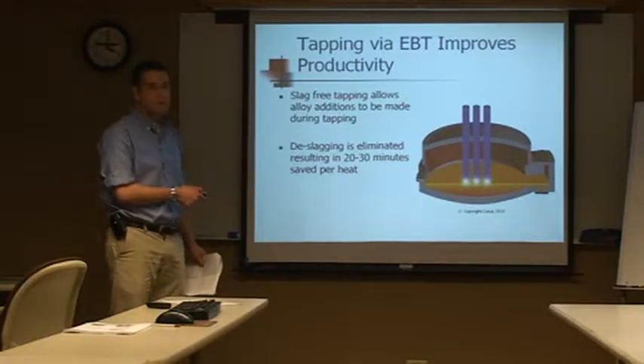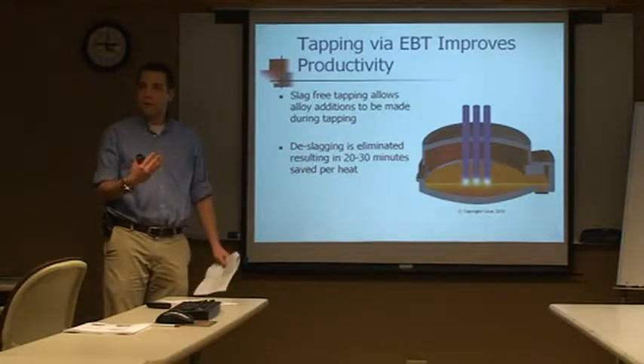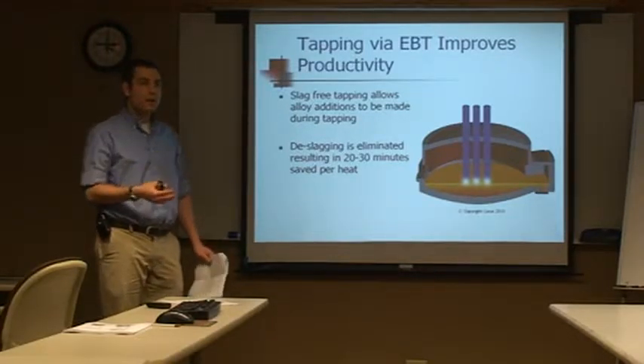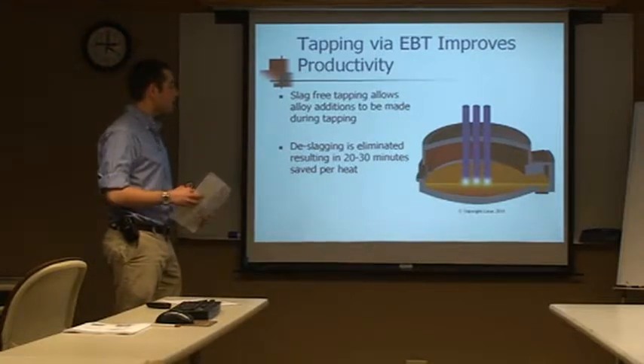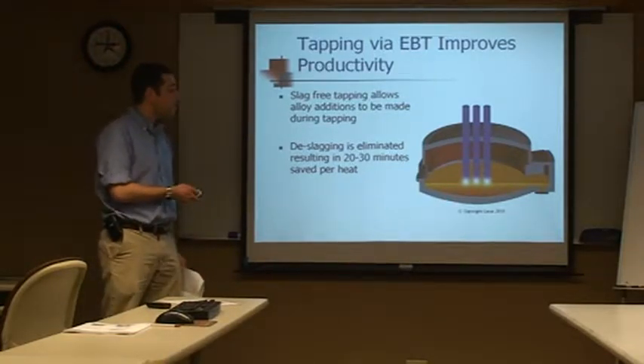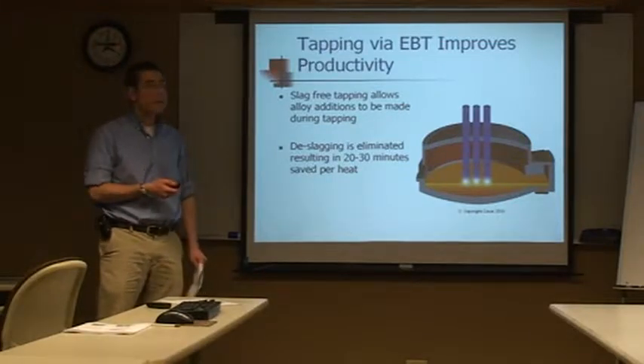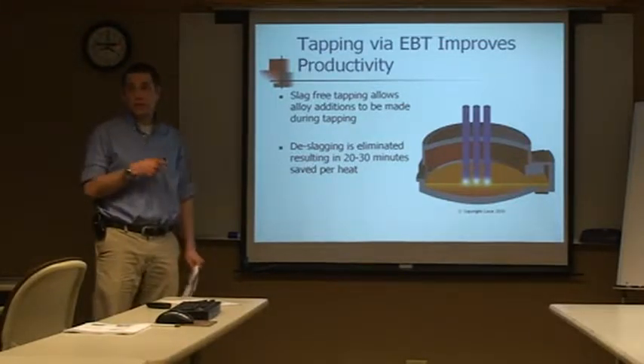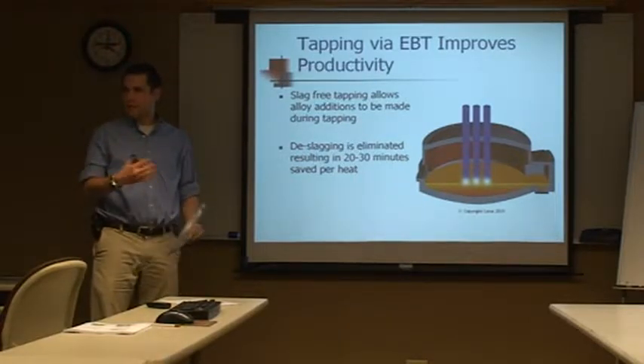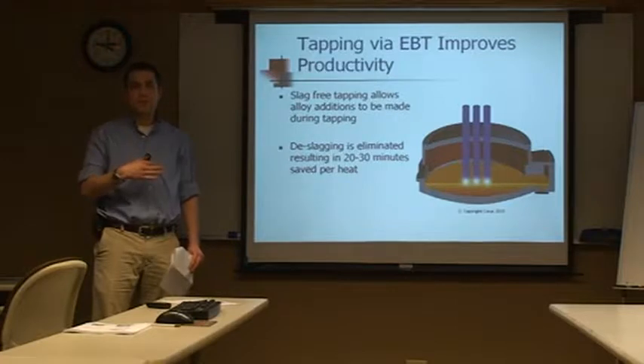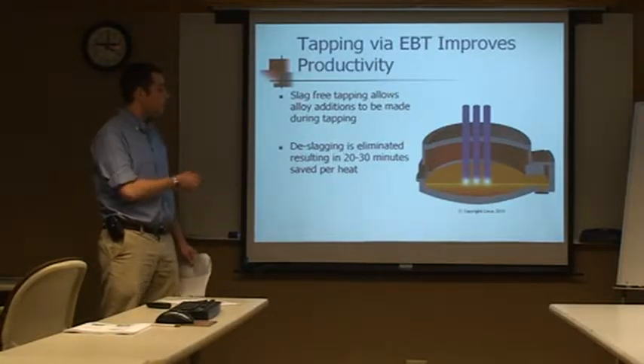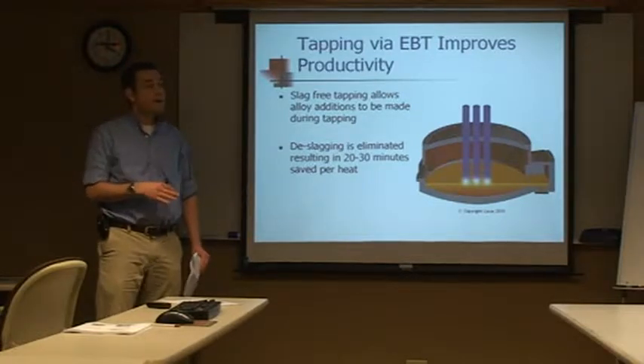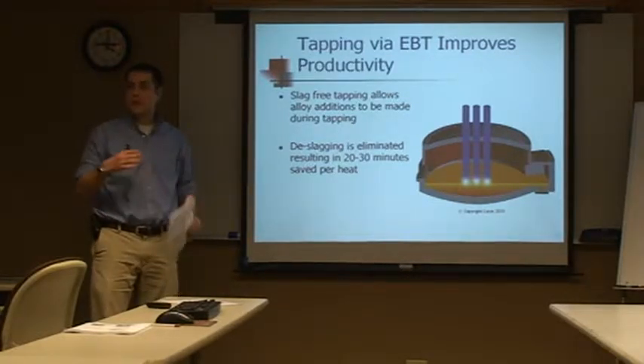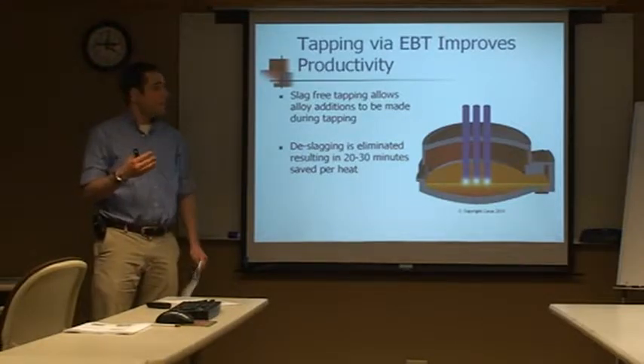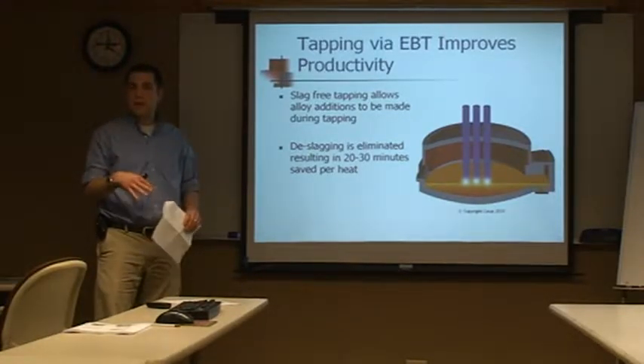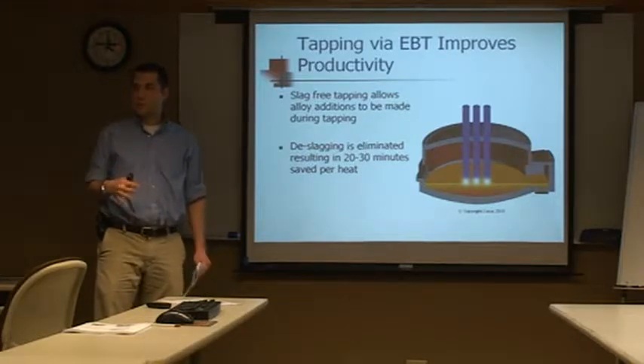The reason it's off-center is to try to cut back on any kind of whirlpool effect that we would have in the arc furnace, because that can wear down the lining of the arc furnace, which we generally want to protect as much as we can. One of the big advantages of an eccentric bottom tap furnace is that you get to keep most of the arc furnace slag, which is the stuff that floats on top and has the phosphorus. We tap some of it out into a slag pot, but there's still some on top. But we get to keep most of that in the arc furnace. It doesn't go into the ladle. And the reason we want to keep that out is because that's where most of our phosphorus has gone. And if it goes into the ladle and stays there, it can revert back into our liquid steel.